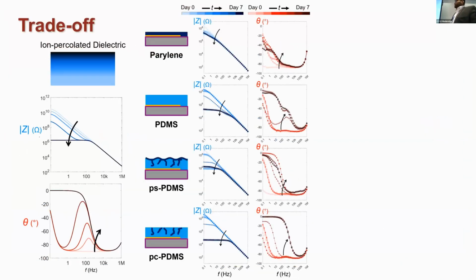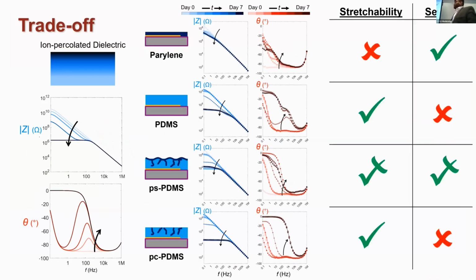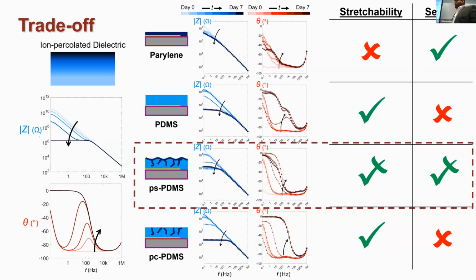So let's review what we see until now. We see the ideal diffusion process and the samples that we tested. So what we see here for the sealing of sensor devices is that there is no ideal material that can show stretchability as well as sealing properties. But with clever engineering, we can find a middle ground where the ps-PDMS is able to provide better sealing compared to the pristine PDMS. And then we can also alter the stretchability of it by some engineering methods. So we think that ps-PDMS is a good candidate for the sealing of sensor devices.